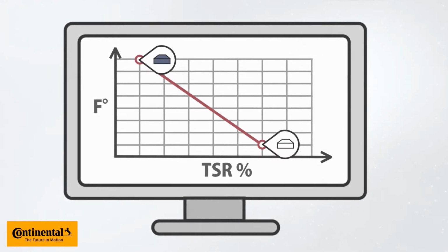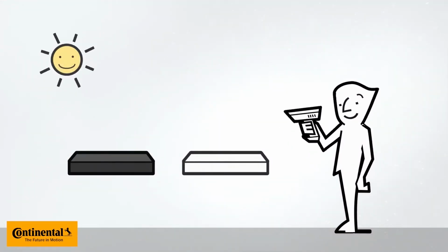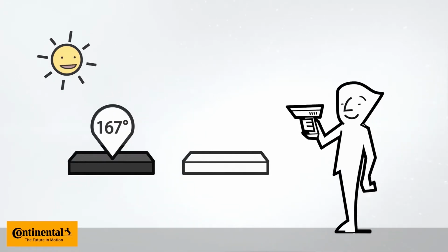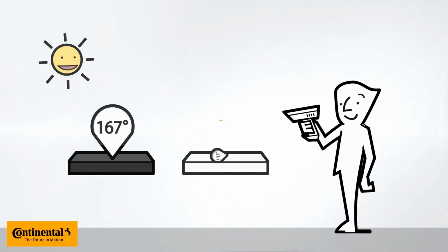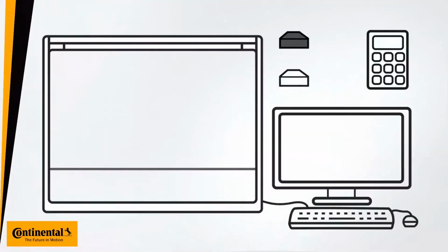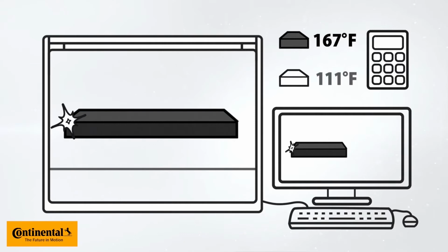Firstly, the black and white standards are measured. For example, in Middle Europe on a cloudless day, and with an outdoor temperature of 102 degrees Fahrenheit, 167 degrees Fahrenheit on the black standard, and 111 degrees Fahrenheit on the white will be reached. These two standards and the specific TSR value of the film can be used to predict the temperature of other shades, such as jet black, on the day of measurement.